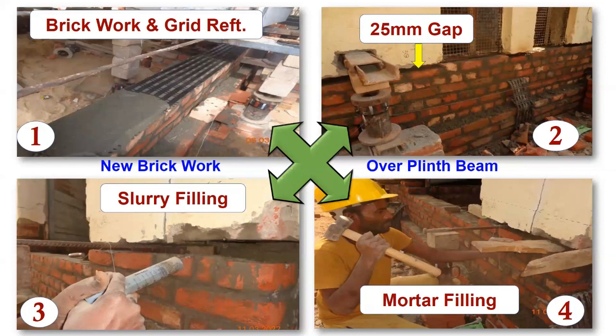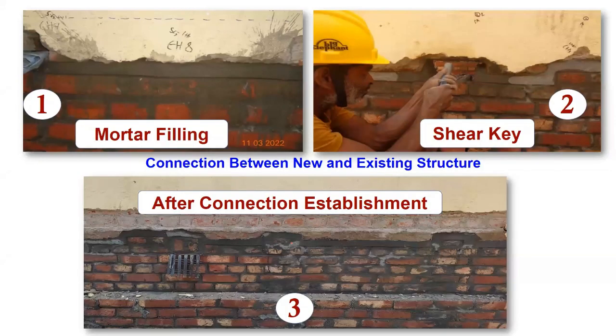And this is how the slot works. This is the old building, and this is the new brick level. This area has a 25 mm thickness, and it will be filled with dry mortar through hammering like this. The surface is first treated using a latex modified slurry coating, and then the hammering was started and it was filled. To ensure proper shear transfer, we made a shear slot like this, a zigzag pattern connection, and geogrid reinforcement is also there. So we have done the plinth protection also.